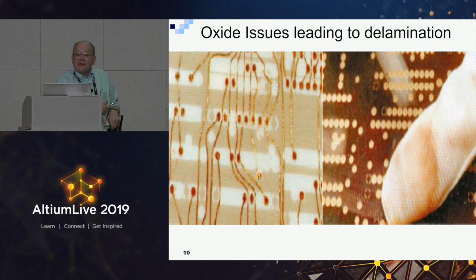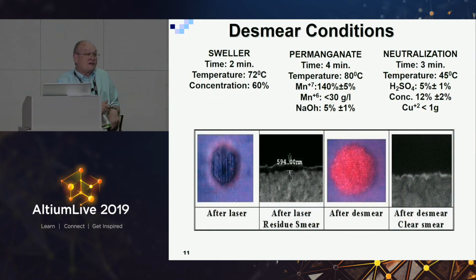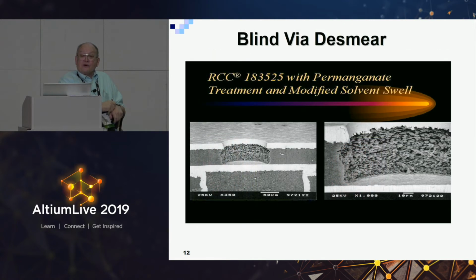Oxide issues lead to delamination on the inner layers. De-smear conditions: after drilling, you go through a sweller, a permanganate, and a neutralization. How do you test that? Make sure that worked effectively. Again, there's a coupon for that. You can see in these electron microscope images that the geometries of these microvias are very, very small. And the permanganate can be done improperly, either immersion time or concentration. When that happens, there's melted epoxy left, especially with CO2 lasers. And the melted epoxy could be over an electrical connection to an inner layer, or it could be only partial.